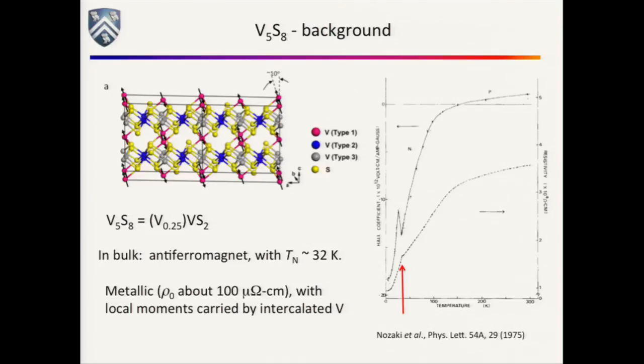which you should really think of as VS2 with an added quarter vanadium. Just like the iron intercalated TMD I showed you a minute ago, you can think of this as a 1T VS2 instead of a 2H VS2. There are vanadiums that live in these chalcogen TMD layers, but there's a third kind of vanadium site, a site in the intercalants. So it's vanadium, a quarter per formula unit, between the VS2 layers.